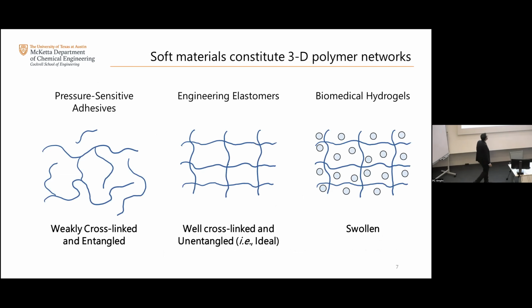Now, why are these materials elastomeric in nature? And now I'm hoping to provide a little bit of a molecular view of what's responsible for this fracture process, and what we understand about fracture from a molecular point of view in order to build a molecular picture of fatigue. What we know is that they're polymer networks, and depending on the level of cross-linking and the amount of defects and the amount of solvent, you can control the mechanical properties of these systems.